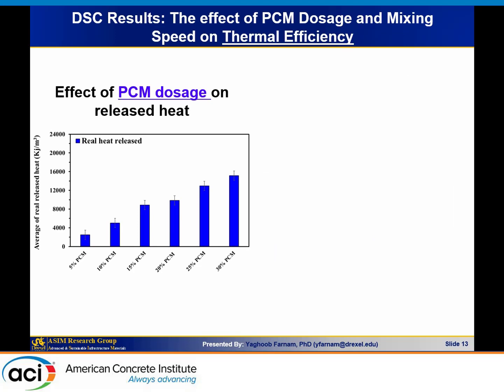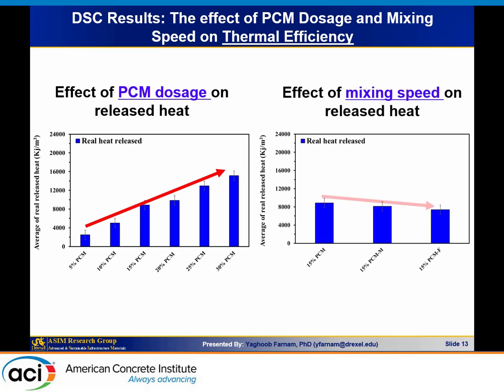And if we do that and we integrate the peak and find out the thermal energy or latent heat of fusion, this is the type of behavior that we're going to get. This is the PCM dosage, from 5% to like 30%. This is the latent heat of fusion, the area under that peak. If we look at that, DSC gives us linear behavior, and this is what we expected. Nothing unusual about that. You increase the amount of PCM, you add more thermal reservoirs, so you're going to increase the amount of energy release in your sample. So nothing very complicated there.